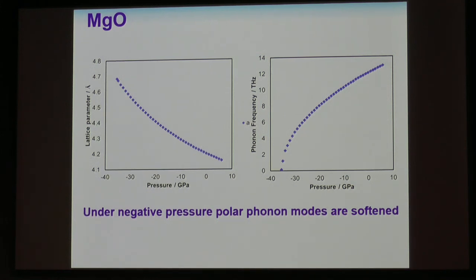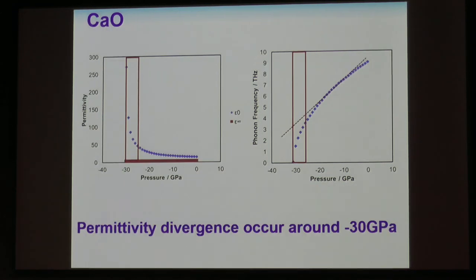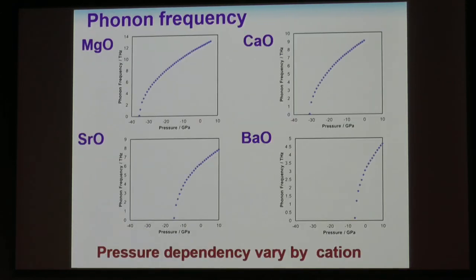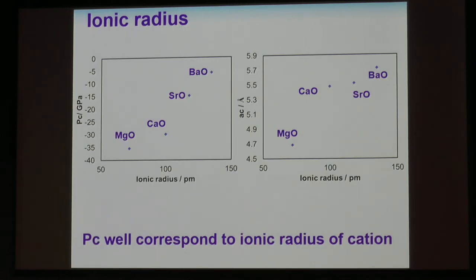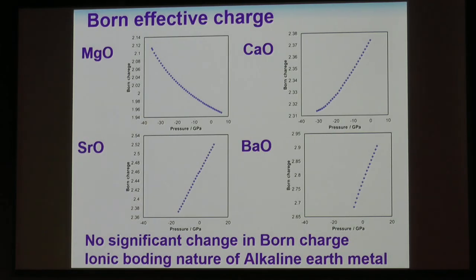Then I have another observation. You say covalence. We have known for a long time that ferroelectricity is associated with very large Born effective charges. And this only occurs because of covalency. Because if you don't have covalency, if you can interpret it in terms of Wannier functions, the Wannier function sits on the nucleus, and so you have a trivial Born effective charge. You don't have any ferroelectric transition. So that seems to me really a new message. Okay.